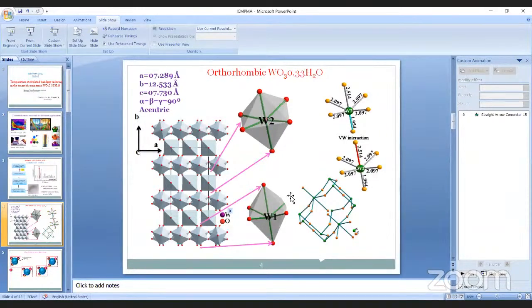There are two types of water molecules in orthorhombic WO3·0.33H2O. One type of water molecule is coordinately bonded to these two types of oxygen atoms, or it is called intercalated water molecules. Thus, the water molecule connected along the C-axis between these two types of WO6 octahedra gives the layered nature to this material. This layered nature is very important when we characterize the material in different fields.